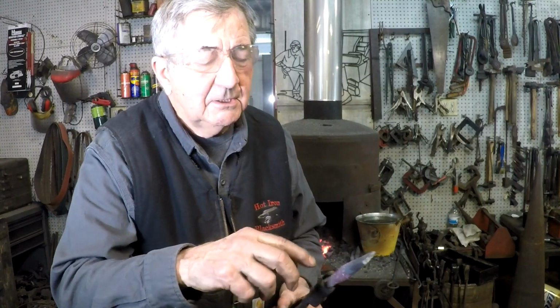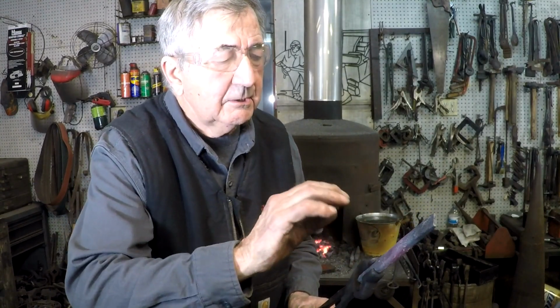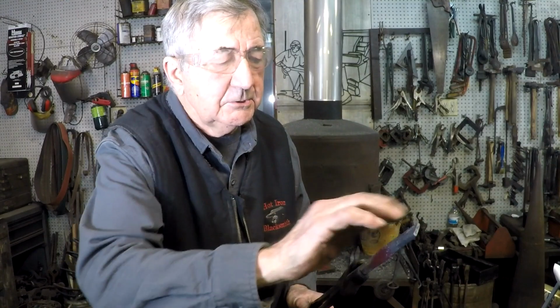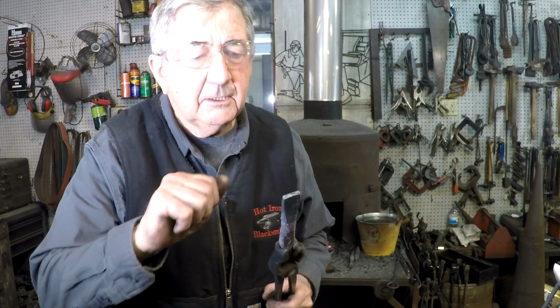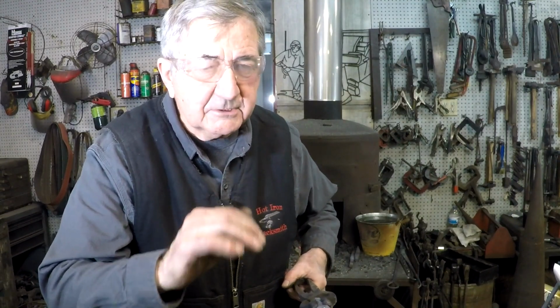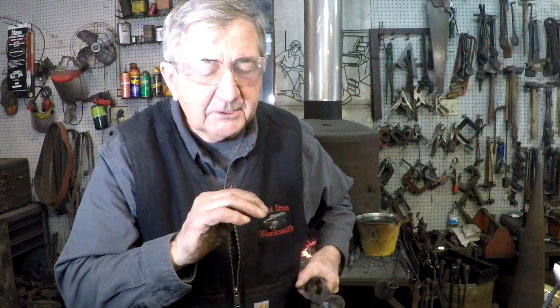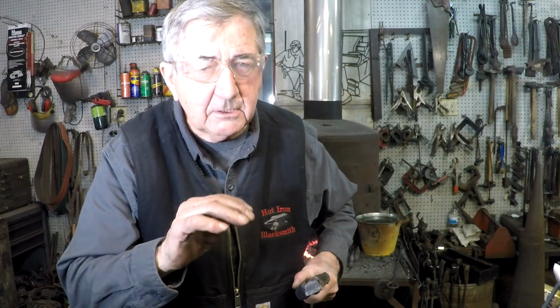Now I'm going to temper, and we're going to temper by using the residual heat that is left in the punch and let that transfer into the end of the punch and warm that end back up to about 400 degrees. Now how do I know the temperature? I'm going to take a small broken grinding stone and scrape off the scale that's on there and make it shiny as best as possible. And then I'm going to watch the colors transfer down to the end of the punch.